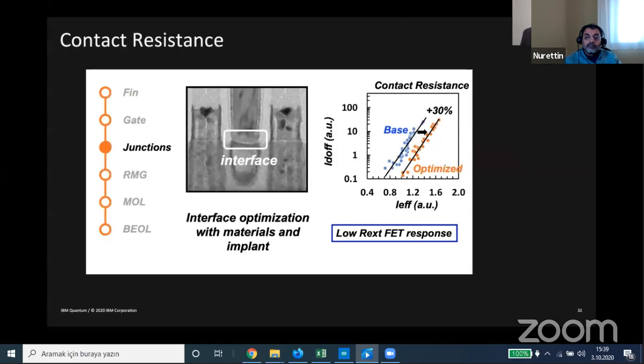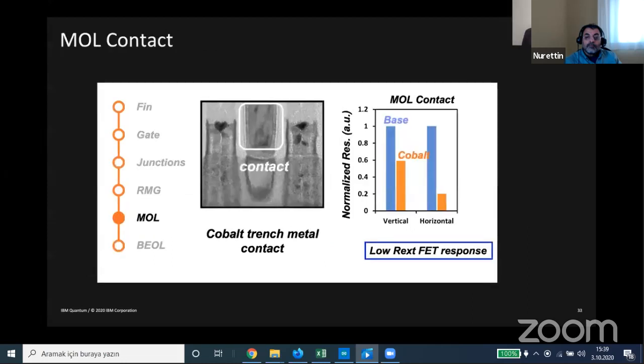Next, the interface was optimized to achieve the lowest contact resistance possible. This did require novel materials at the interface to form the best silicide possible with low resistance, and also the introduction of a shallow implant to lower the contact resistance. The net was a 30% boost in performance.